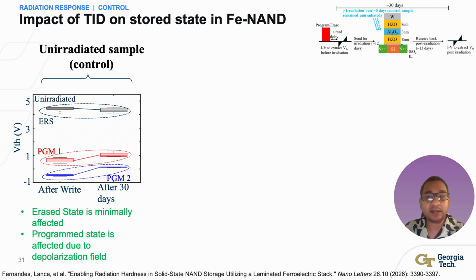We associated that program state relaxation mainly with the depolarizing field and the normal retention behavior. This is why a control is essential. Without it, one could incorrectly attribute every threshold voltage change after sample transport and delay to radiation. The asymmetry between the erased and the program relaxation also warns us against describing the stability with only one state. The useful memory window depends on the movement of the threshold voltage for both the programmed and erased states.